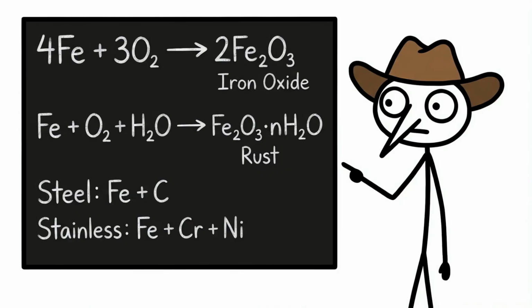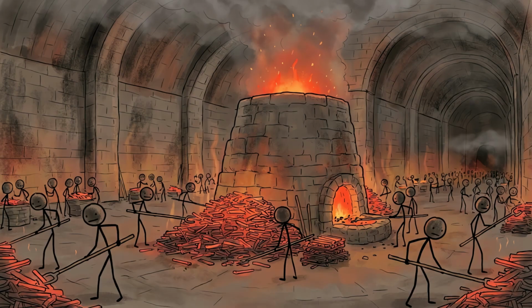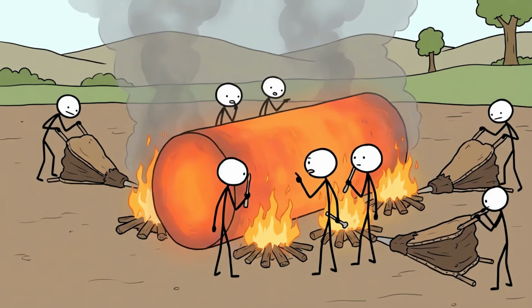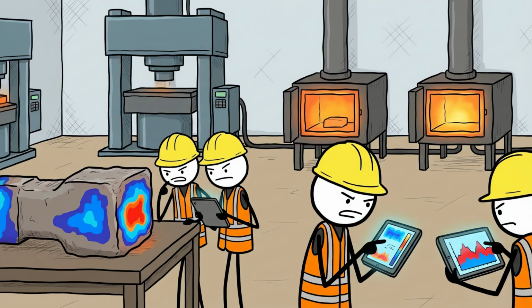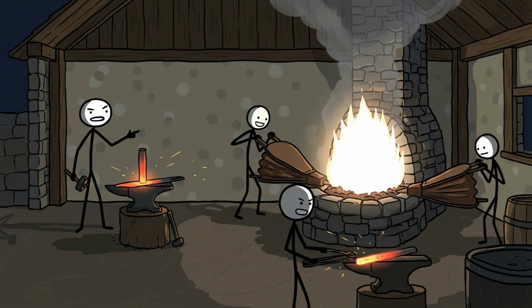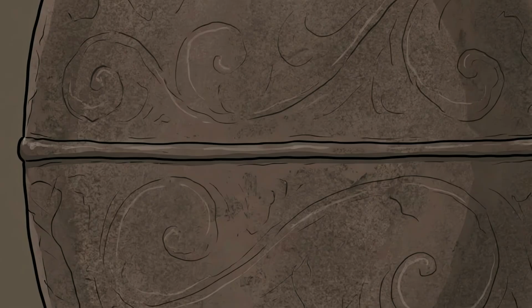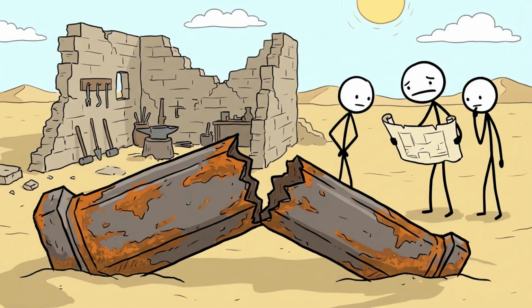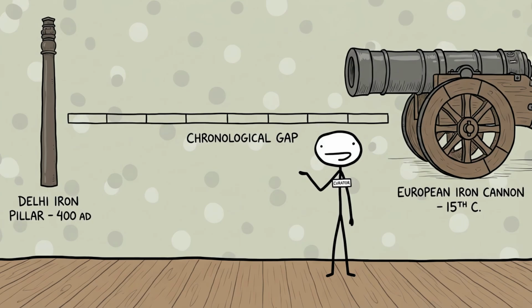But the protective film theory doesn't explain the forging itself. Creating a 6-ton wrought iron pillar requires welding together hundreds of smaller pieces, while maintaining even temperature throughout the entire mass. Modern forges struggle with such uniform heating. How did 4th century smiths achieve it using charcoal and bellows? The precision required to prevent cold joints or weak spots is extraordinary. One mistake and the whole thing fails. Yet they succeeded on a scale not attempted again for over 1,000 years.